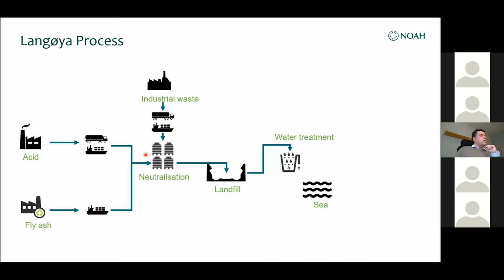Into this neutralization plant, we can also add other kinds of industrial waste. This could be wastewater, other kinds of acids, and also alkaline material, as slurries. After the neutralization plant, it's a slurry, we call it gypsum slurry. It's pumped into our landfill, and the solids settle, and excess water either goes through our water treatment system, where it's cleaned and pumped to sea, or is pumped back into our fly ash slurification process. So this is our current process at Langøya.